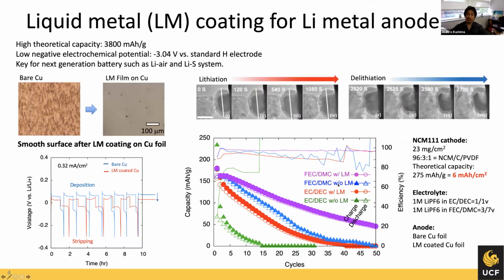So in my research, I've been developing different lithium-ion battery anode and cathode materials, and here is one example. The lithium-ion battery is already a high energy battery, but you want to extend it with a higher capacity anode, and one of them is lithium metal. If you can use lithium metal as the anode, you can increase the anode capacity by 10 times compared to the current graphite.